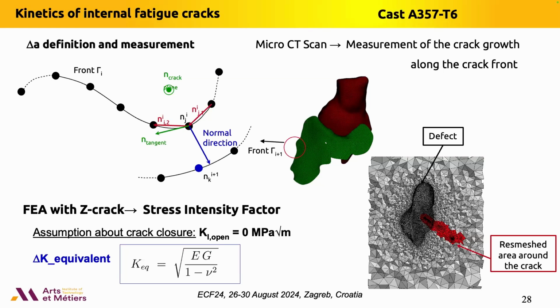And we have assumed that the crack closure can be taken into account in a very simple manner because, unfortunately, under ultrasonic testing, we are not able to know what the opening load is. So a simple way is to consider that the crack is open as soon as we consider only the tensile part of the fully reversed loading. It means we have neglected the compressive part of the cyclic loading. And to consider that the crack interacts with the microstructure, it means it propagates in a mixed mode. We have computed the range of the equivalent stress intensity factor according to the strain energy release rate.